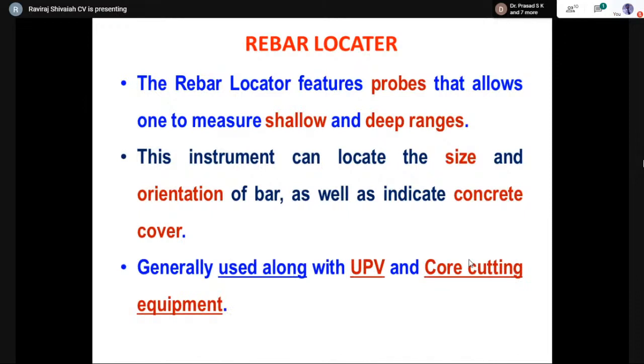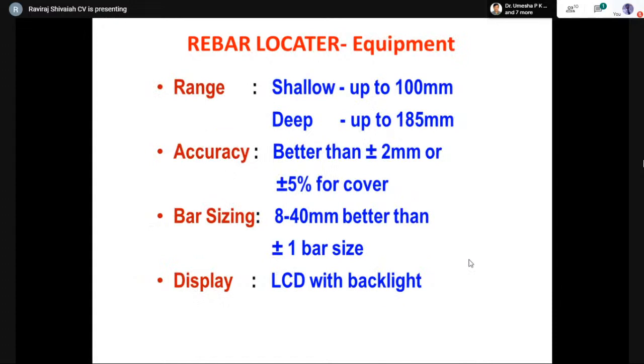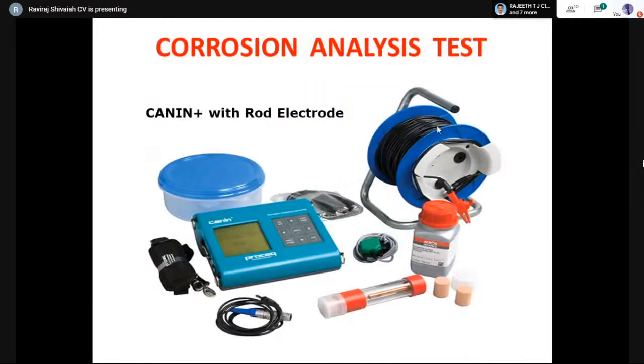This is especially important when we are trying to do tests of UPV, that is ultrasonic pulse velocity, the previous test, and the concrete core cutter. So I'm trying to tell you, shallow probes are good up to 100 mm, deep probes are good up to 185 mm, okay? Right. Now let me go to the next instrument that we have here.